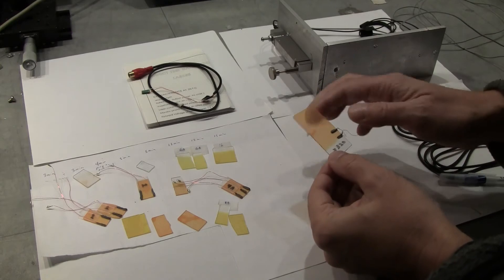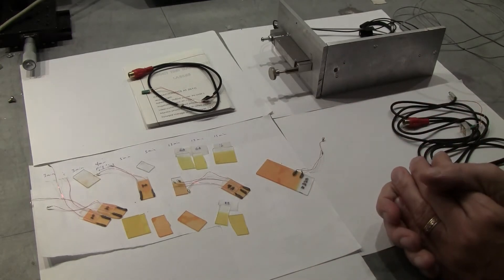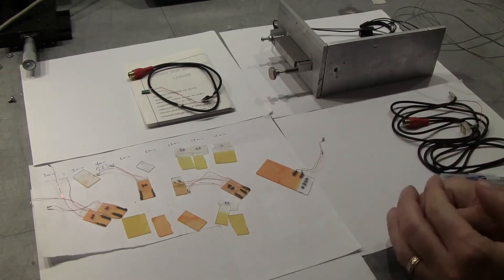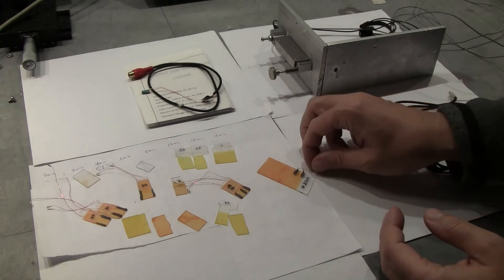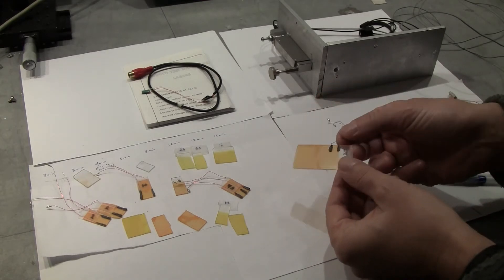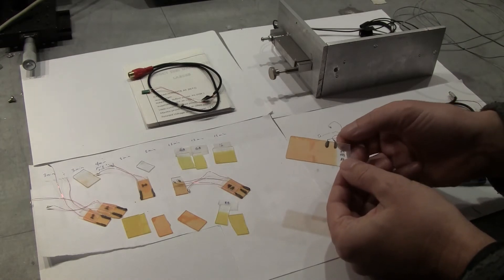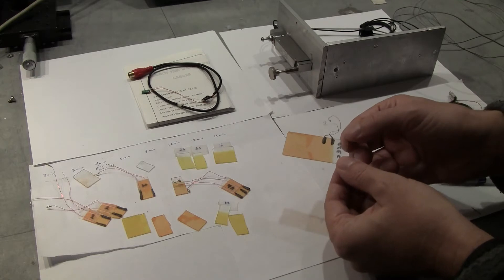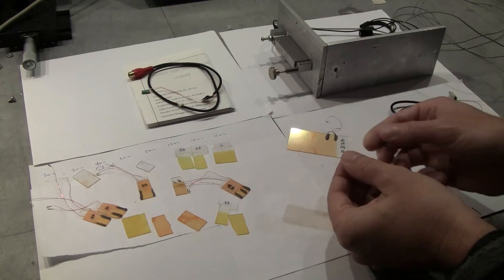What I've got shown here are some sensors that I worked on. It took a bit of practice to be able to cast cadmium sulphide into very thin films down to around that range that we wanted to reach. But because cadmium sulphide is like a simple photoresistor, once you've got the film cast, you just need to put contacts onto the film, and then you can measure just by the resistivity of the film as the beam is passing through to try and detect your interference signal.